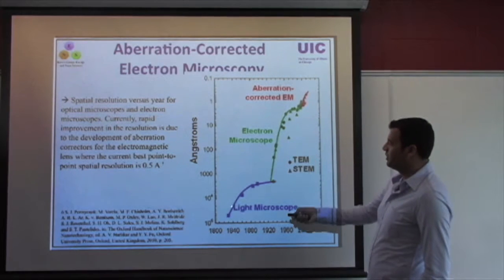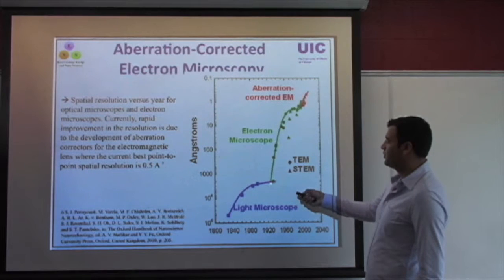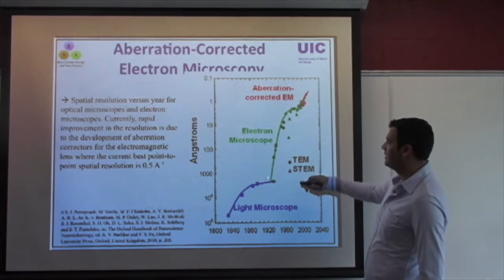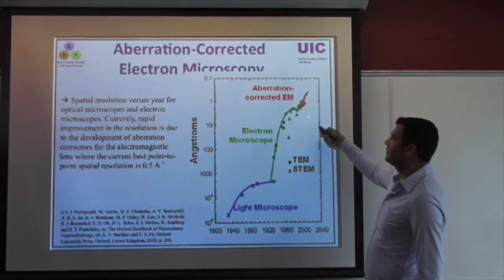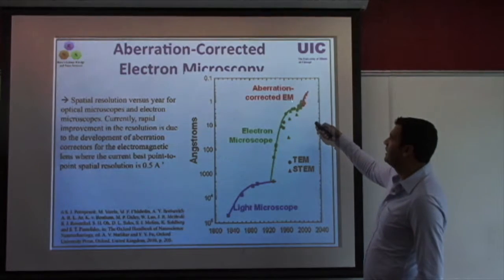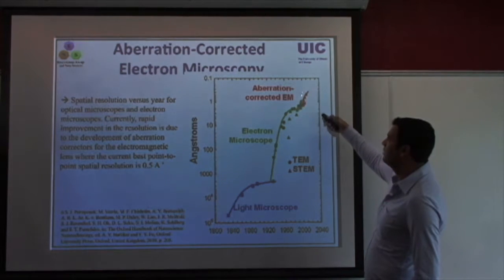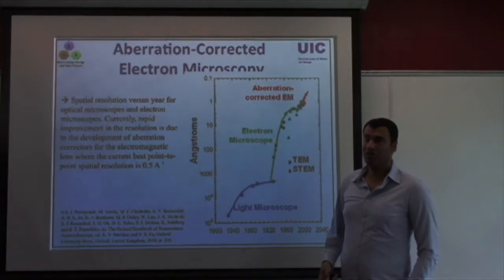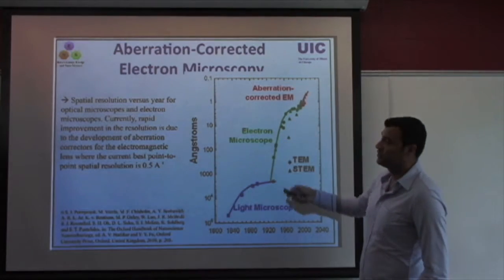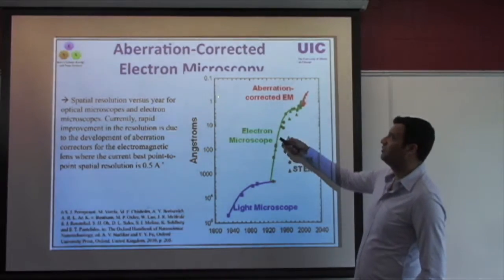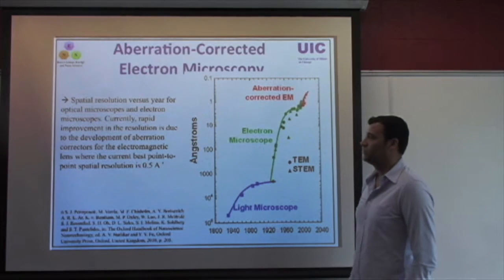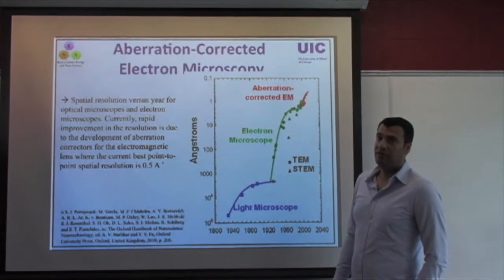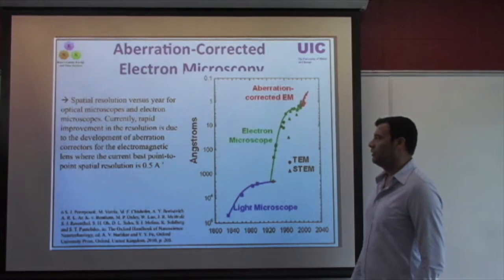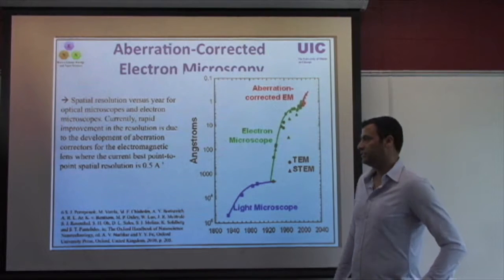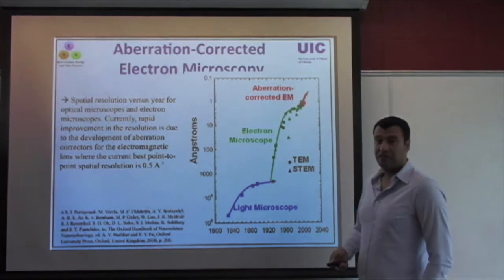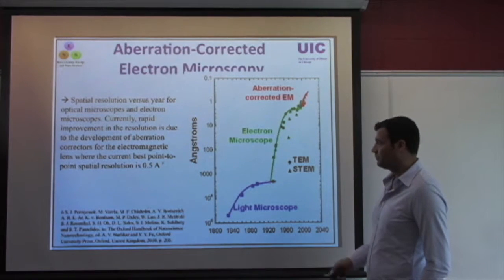So by that innovation, when light microscopes were changed to electron sources, the resolution reached about an angstrom, and maybe a little bit lower than an angstrom. And then with the aberration-corrected microscope, we have had several fold of improvement in resolution, and now we have reached a point that we can do maybe about 0.5 angstrom, and people are still pushing this to go below 0.5 angstrom. But this should be good enough to look into the individual atoms, and that's unprecedented resolution capability that you can gain.